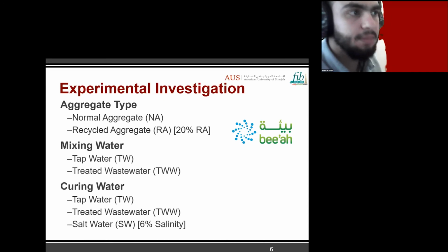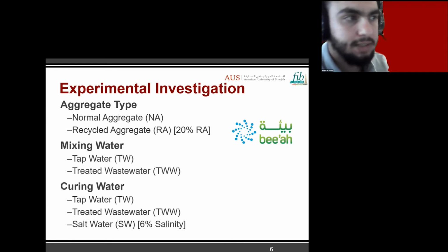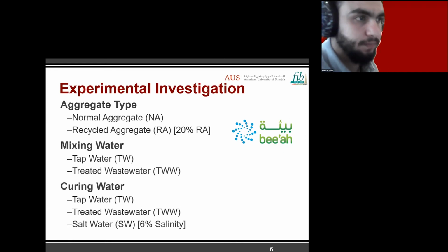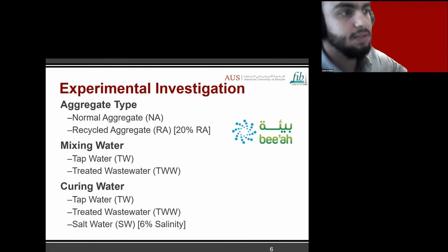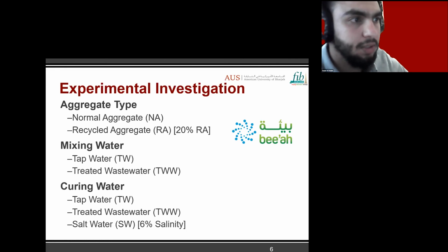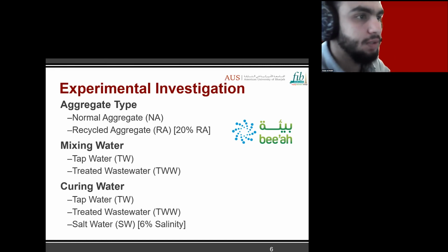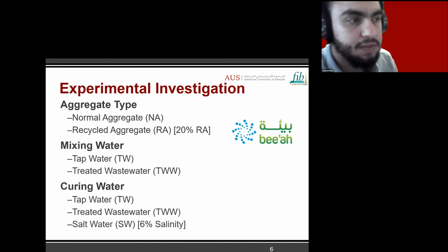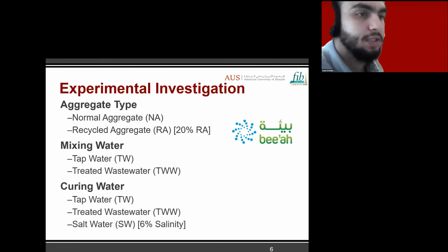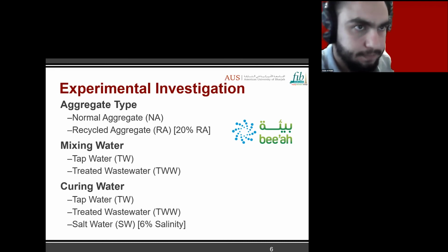The second parameter that will be considered is the mixing water, where we will consider using fresh tap water against treated wastewater. Curing and exposure conditions will also be a parameter where the mixes will be exposed to tap water, treated wastewater, and salt water with 6% salinity. The use of salt water is to simulate the harsh environment condition.